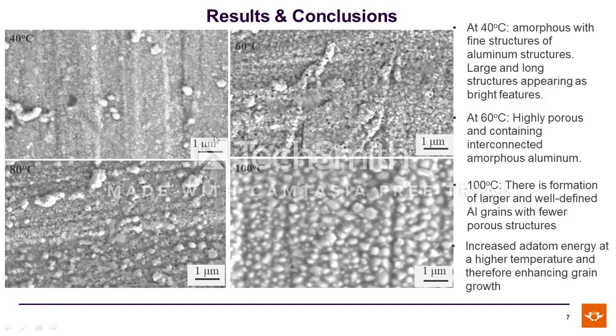So our SEM results show that at 40 degrees Celsius, the microstructure consists of fine amorphous aluminium structures. There are also occasionally large and long structures appearing as bright features shown. But at 60, the structure appears highly porous with peaks of pores and long channels of porosity on its surface. However, increasing the temperature from 80 to 100, there is formation of larger and well-defined aluminium grains with fewer porous structures. These results can be attributed to the fact that increasing temperature increases the adatom energy on the surface of the substrate and hence enhancing grain growth.